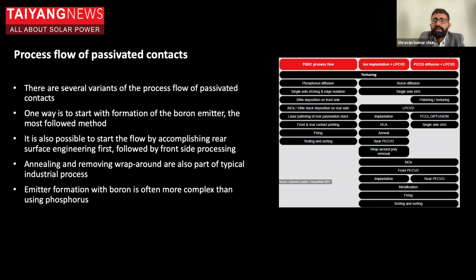And here, when you compare to the PERC, the application of the rear stack comprising of tunneling oxide and polysilicon layers, replacing the aluminum oxide deposition are the very obvious changes. But then whether the polysilicon layer which is applied is doped in situ or external, this also determines the process flow. And irrespective of the deposition technologies, which I will cover later, so the process definitely requires some additional cleaning steps on the front side, and a few steps more compared to PERC are emitter formation with boron, which is often more complex than the typical phosphorus emitter formed with the PERC cells.